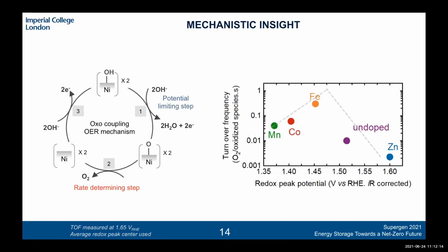So based on this proposed mechanism, we can explain why we have different trends as a function of doping. So for example, if we plot the turnover frequency as a function of the redox peak potential, which is basically a proxy for the binding energy of oxygen on these different doped nickel sites, what we see is we have this characteristic volcano shape. So going from iron to the manganese doped case, we know that the manganese binds oxygen too strongly, so it's quite easy to form these oxidized species, but this final oxygen removal via this oxo coupling is what probably limits the overall rate of the reaction.